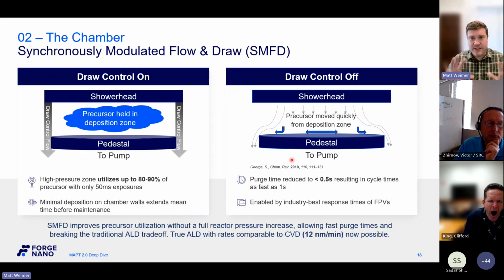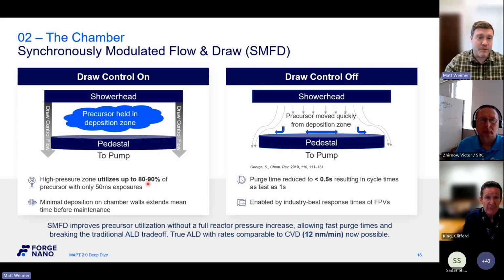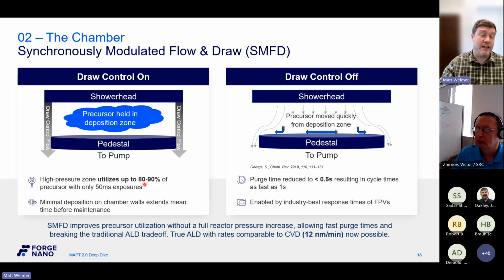Now, this is highly dependent on a lot of things, so this is a very simplified example. But just to kind of put some numbers on it, for some processes, we can get up to 80 or 90% efficient. For our slow processes, we introduce precursor for 50 milliseconds. But for, say, TMA water, we'll introduce TMA for 5 or 4 milliseconds. That draw control also helps us to keep some of that precursor off the chamber walls.